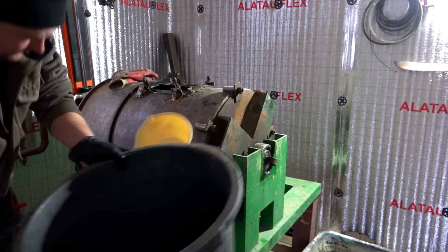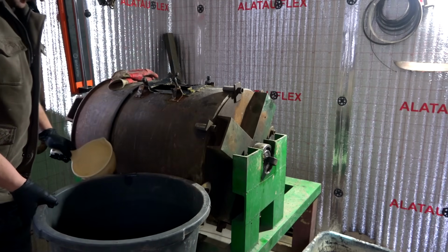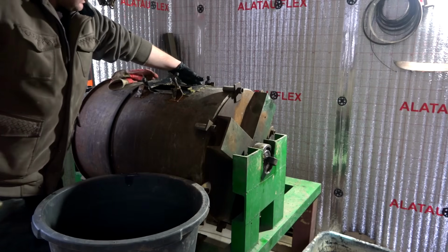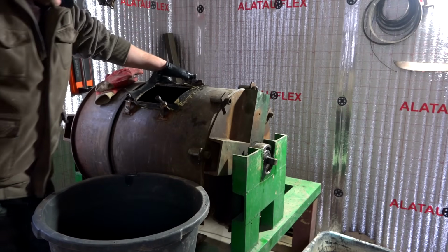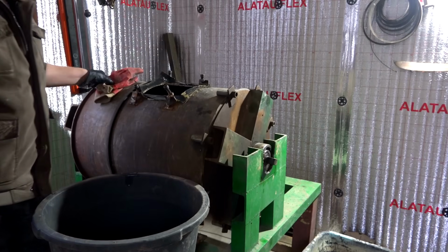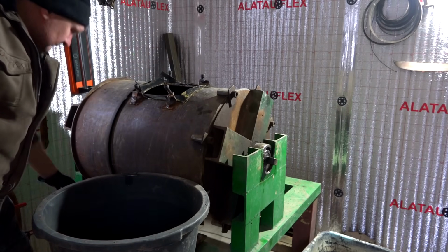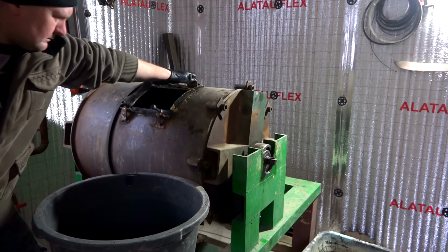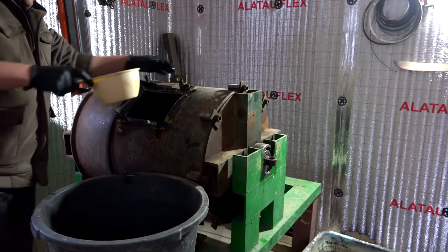Now, dear viewers, I've adapted and operate this way. I fill the crusher, then crush the material for several hours, and then use a scoop to scoop out the contents through the loading hatch and wash them in a centrifuge. Then I reload the crusher and repeat this process until it's completely exhausted.